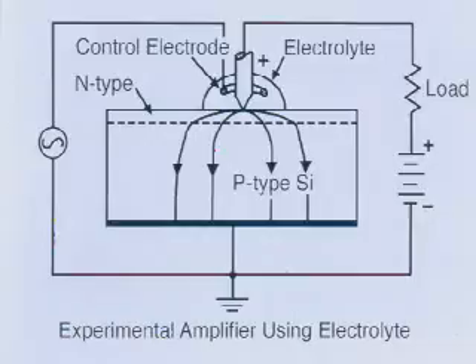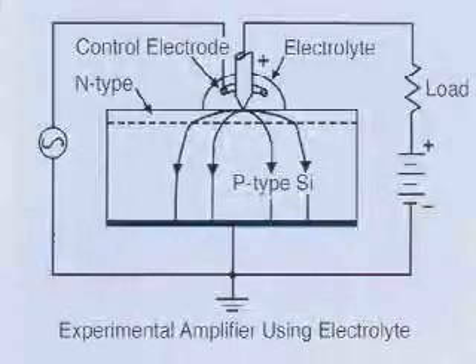But it was no good in a certain sense to those of us who do electronics, because this electrolyte is slow. So they felt, okay, we'll replace that. They checked this out in germanium after they did silicon, and then decided they'll put a gold disc here on top of germanium, put a hole in it. The gold disc will sit on top, the outside. Underneath it will be an inversion layer. That will be the spreading resistance. And the contact to the spreading resistance will be through this hole.